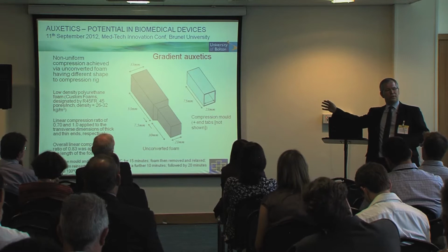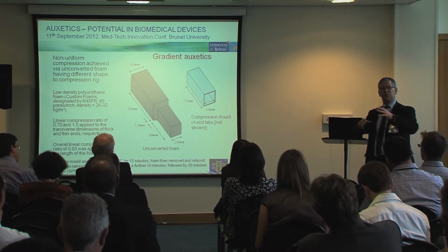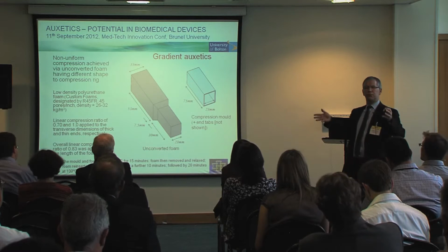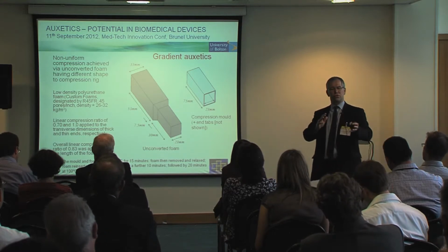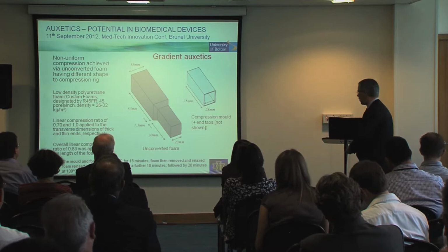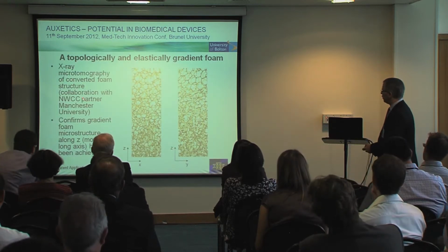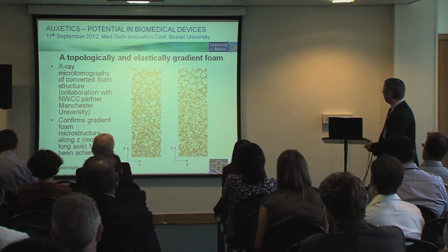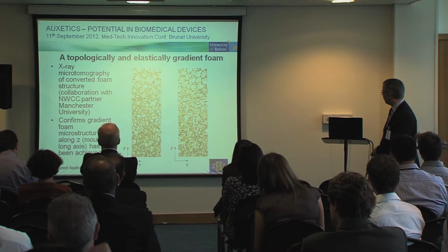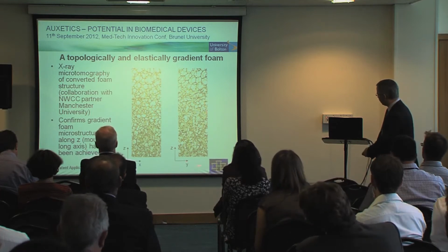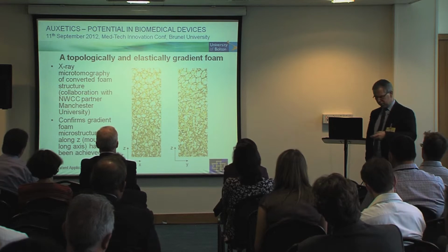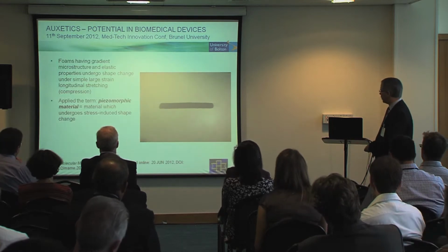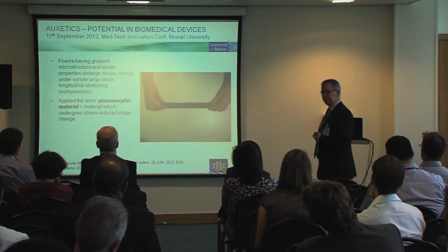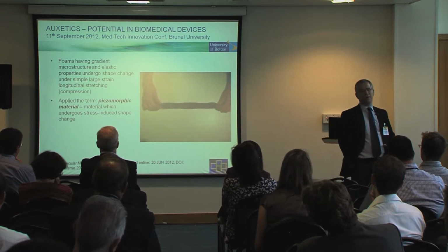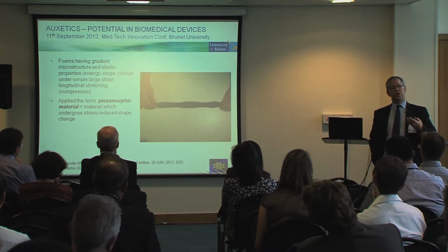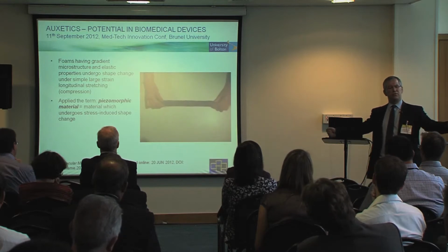We've adapted that process to give us non-uniform compression regimes so that we can vary the amount of compression during the conversion process and therefore change the structure in space. Okay, and this is the tomography work that we do with Phil Withers' group in Manchester. So this structure is characteristic of the normal foam that we start with, and as you go down the thickness, we get into this more contortuous, twisted topology that we know is the auxetic structure. And one of the things that you get then, once you can vary the structures, you vary the elastic properties, and therefore we now have developed a simple shape change material that changes shape just on simple uniaxial stretching.